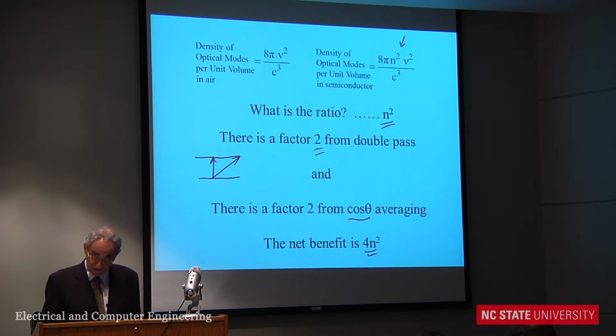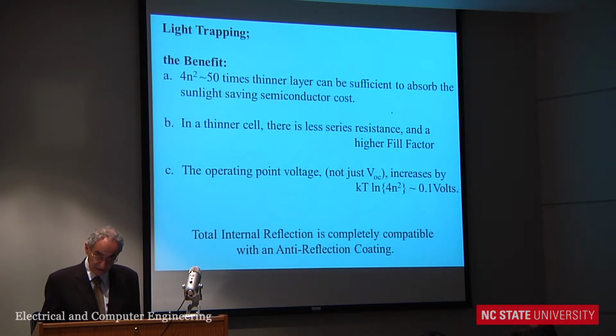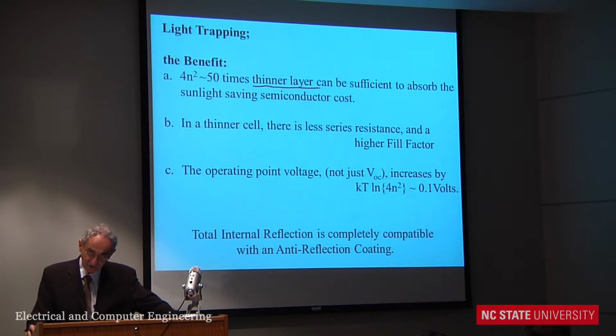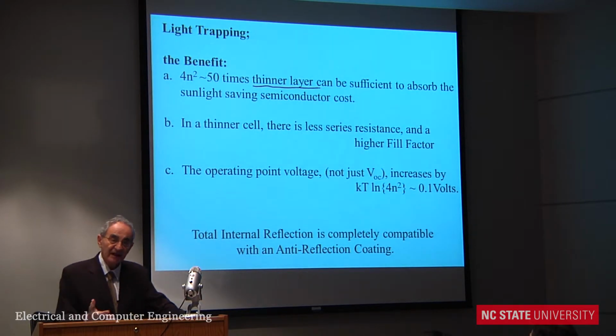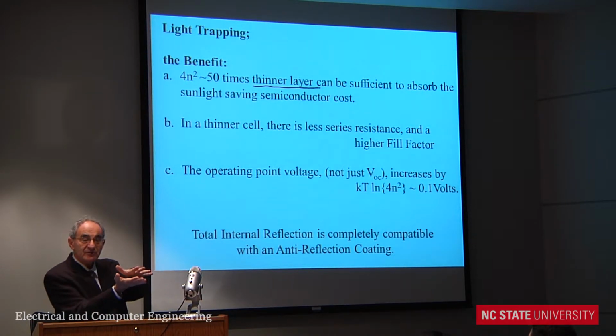And that has a huge effect on solar cells, LEDs, and is important in optoelectronics. Now, so what is the benefit? Well, you can use 50 times less material. Hey, if you're worried about the cost of the material, 50 times less. That's not bad. Okay, and then if you have a thinner cell, maybe the current doesn't have to go as far. There could be less series resistance. But by far, the most important point is that you have taken the electrons and holes produced by sunlight, and now you have crammed them into a thinner solar cell.